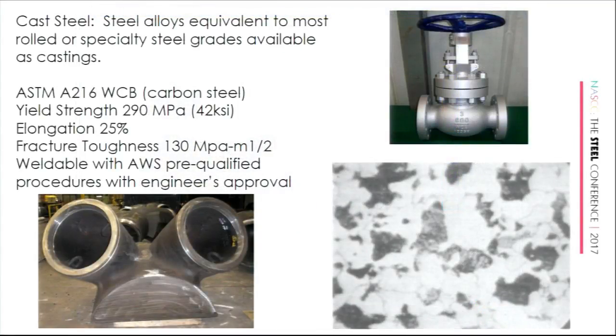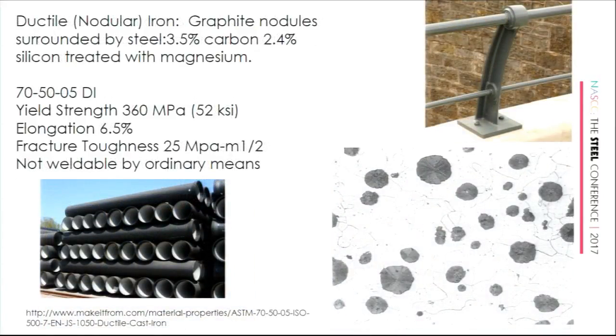So this is steel castings. WCB is a carbon steel. It's really a 30 KSI minimum, 42 KSI typical yield strength, 25% elongation, and it's weldable with the AWS pre-qualified procedures with the engineer's approval. So you can't just use it directly, but if you have the engineer's approval, it certainly is capable of using those weld procedures. There's one other cast iron, since that's part of your requirement, and that's ductile iron.